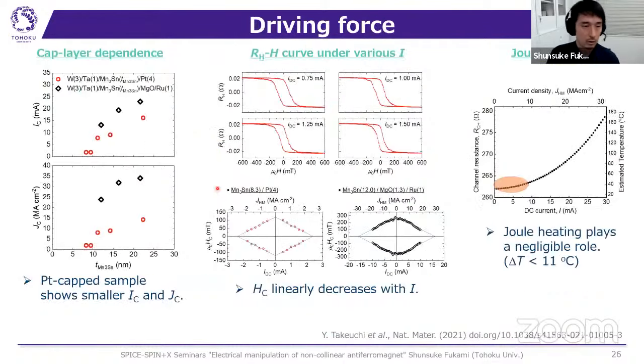Okay. So next we identify the driving force to induce this peculiar phenomenon. First we change the cap layers from platinum to MgO and ruthenium. As you know, the MgO is expected to generate negligible spin orbit torque. So a much larger current is expected to be required to induce the characteristic response of the Hall resistance. And indeed, the platinum capped sample shows a much smaller threshold current and threshold current density as shown here. The red plot shows the results of the platinum capped sample.